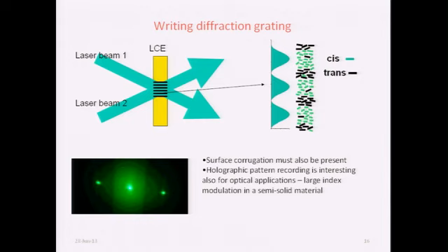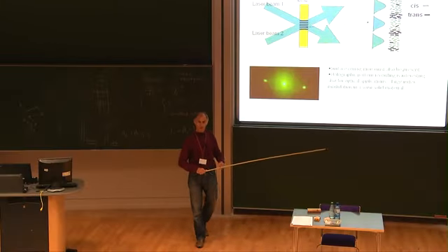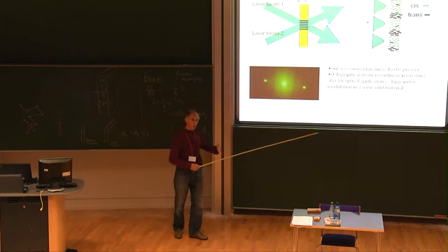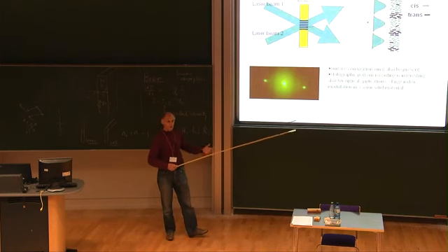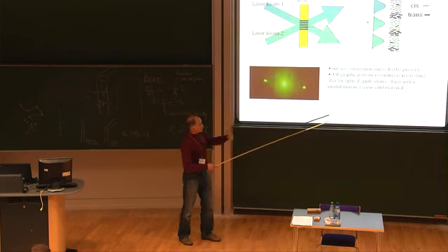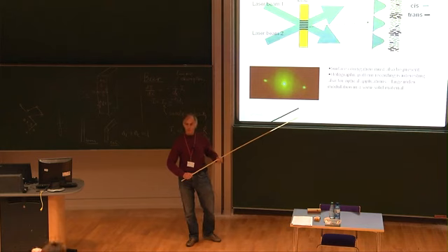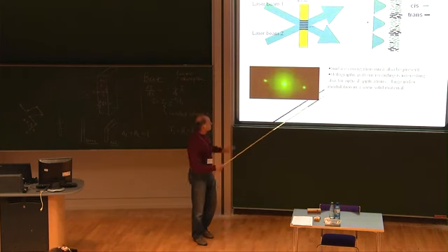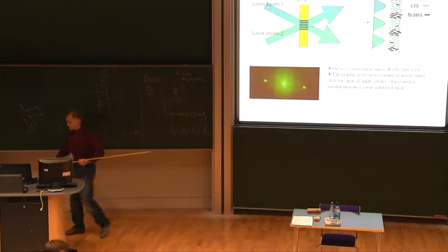I will not talk about it, but let me just remark that the absorption of azobenzene is strongest when it's in the trans configuration, when the light is polarized along the axis of azobenzene. So this is something that can also be exploited quite profitably, especially in polydomain elastomers, where by choosing polarization, you can choose which domains you excite, and therefore choose in which direction the sample will, for example, bend. Also, the diffraction properties of the resulting grating depend on the polarization, and that can be exploited too. But since this is quite complicated, I will not look at it now.